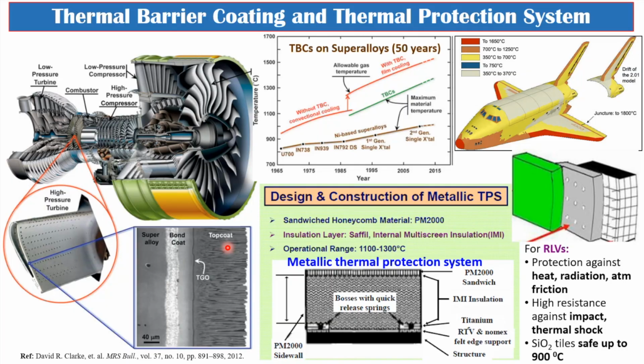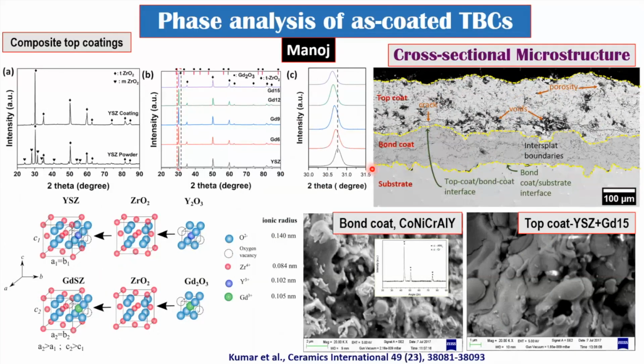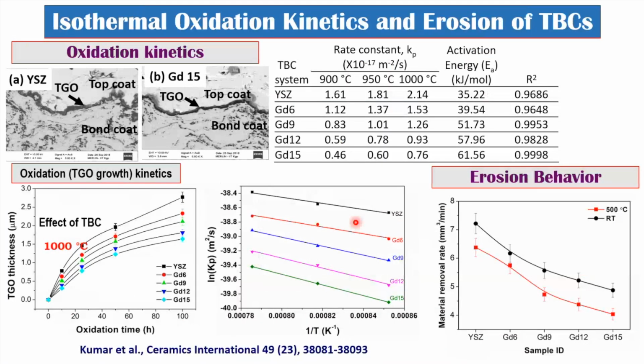Now, one of our students, Manoj, developed this approach. He argued that instead of typically relying only upon yttrium-stabilized zirconia, he varied the level of addition of gadolinium oxide, Gd2O3. In the process, this would typically be the cross section: this is the top coat, the oxide coat which is the thermal barrier coating, a bond coat, and then a substrate. He was able to show that by substituting some of the yttria or zirconia in the zirconia matrix with gadolinium, the same trivalent cation, you're able to reduce the thermal conductivity significantly.